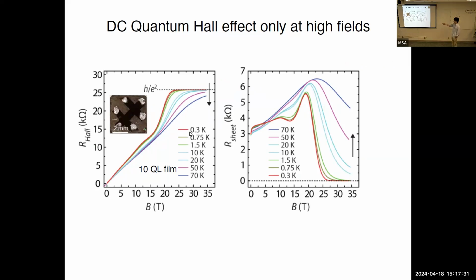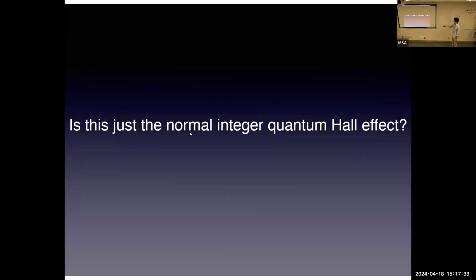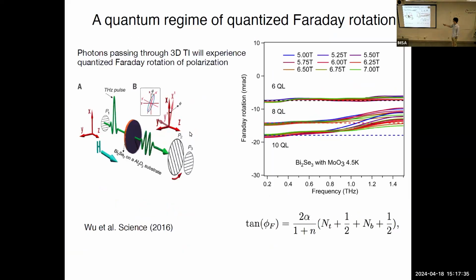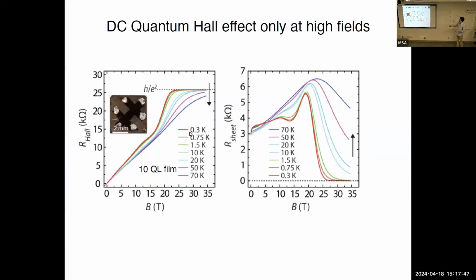And these measurements were actually done on the same sample as we did the Kerr rotation measurements. The difference is that in optics, we were able to see the quantized effect at 7 Tesla, even at 6 Tesla. But in DC transport, you have to go all the way to 20 Tesla to basically gap out those side edges. That's both a feature of a 3D TI, but also a bug, because you have to overcome it to see any sort of quantized effect.